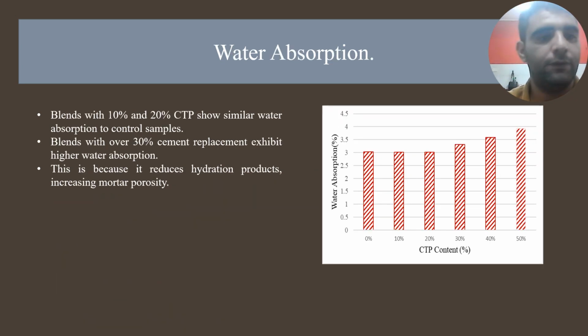In the end, the water absorption. We can see in the figure the effects of ceramic tile powder on the water absorption of the mortar. Based on the figure, blends with 10 and 20% CTP show similar water absorption to the control sample. Blends with over 30% cement replacement exhibit higher water absorption. This is because of reduced hydration products and increased mortar porosity.